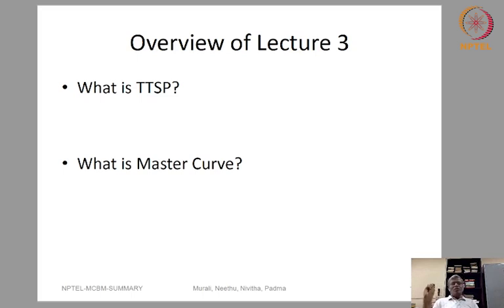To give an example, if you have recorded measurements at 15, 25, and 35 degrees centigrade, and if you have made measurements at, let us say, 4 different frequencies at each of these temperatures, let us say 1, 2, 5, 10 hertz, and if you really want to find out the material functions at, let us say, 27 degrees centigrade for 3.2 hertz frequency, by using the time temperature superposition principle, one can find out the appropriate material function at any intermediate temperature or intermediate frequency.